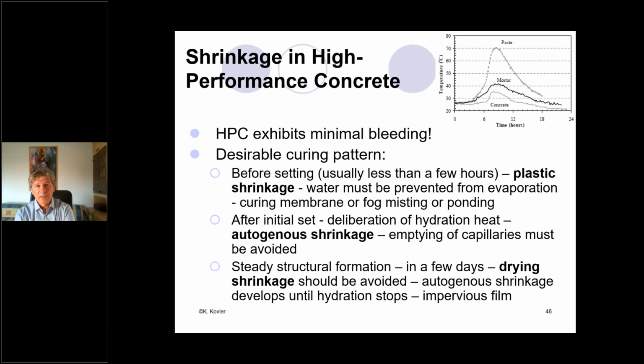Now I'm coming to high strength or high performance concrete. First thing to mention would be minimum bleeding in high performance or high strength concrete. And this bleeding is very important to compensate evaporation of water when we speak about plastic shrinkage and plastic cracking. This shrinkage is extremely important for very hot climate, and not only for very hot climate. It can happen easily in very cold climate when the wind speed is high. For example, in Norwegian fjords, we have extremely high wind speed. So the evaporation rate is a direct function of the wind speed, of the temperature, by the way, not only of the ambient air but also of the internal temperature of concrete, and the relative humidity of the air. All these four components are extremely important, and this evaporation can be nicely compensated by bleeding.